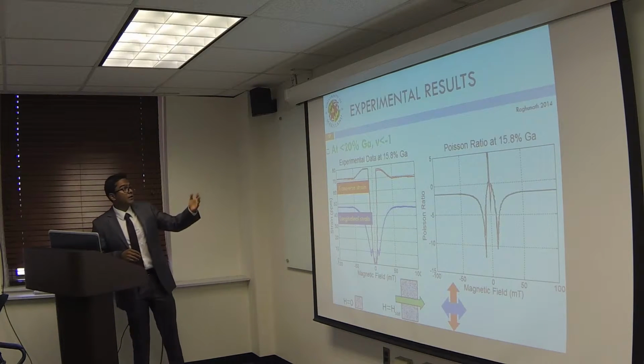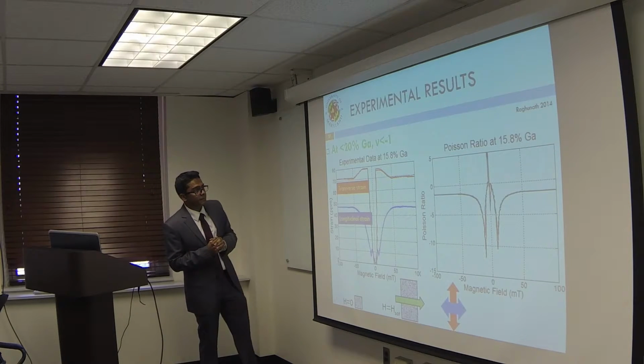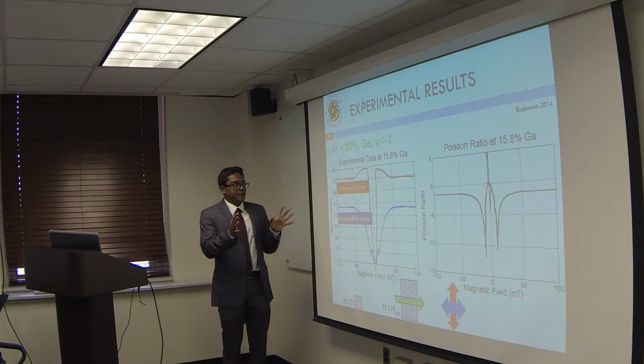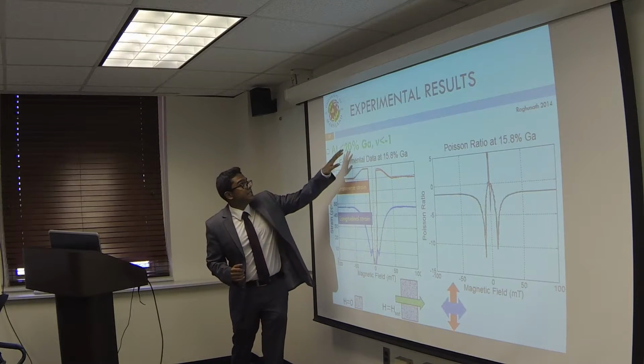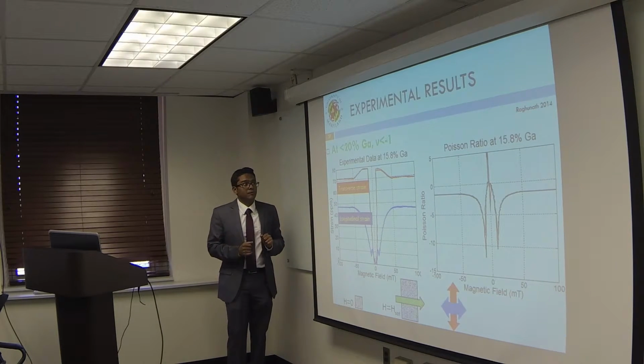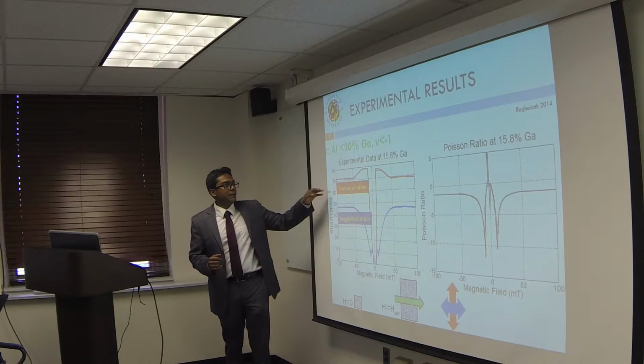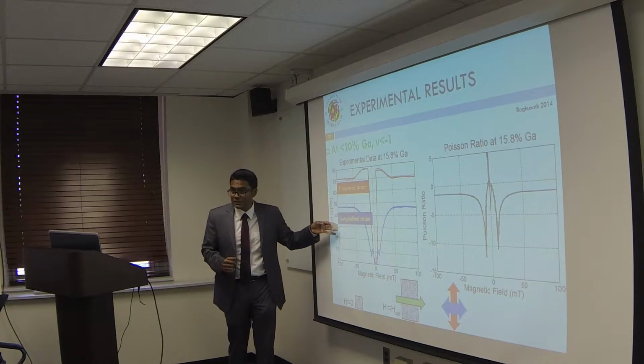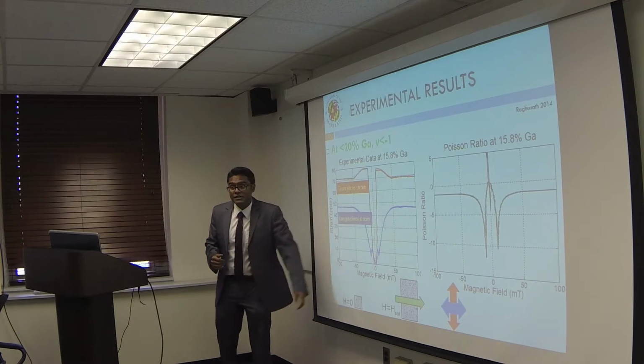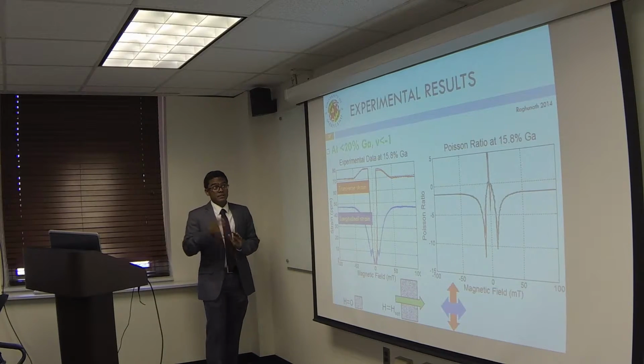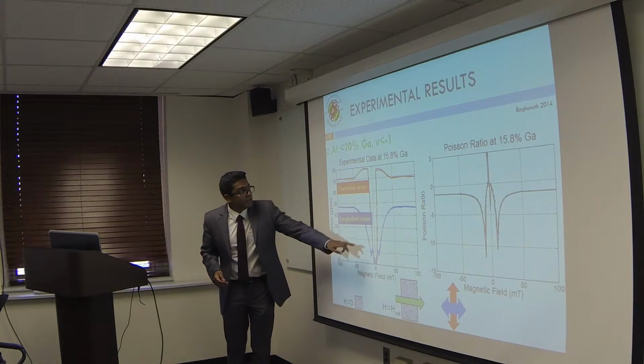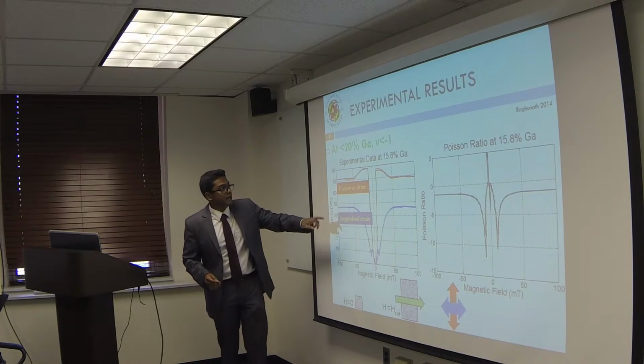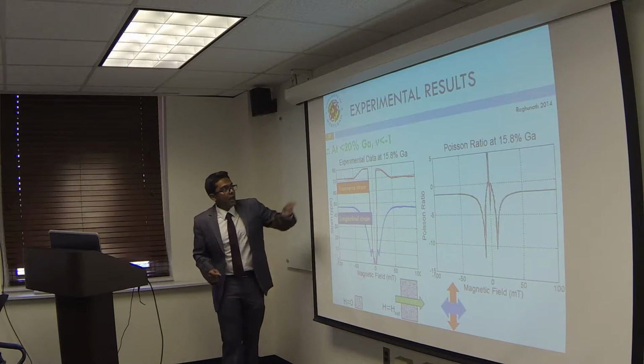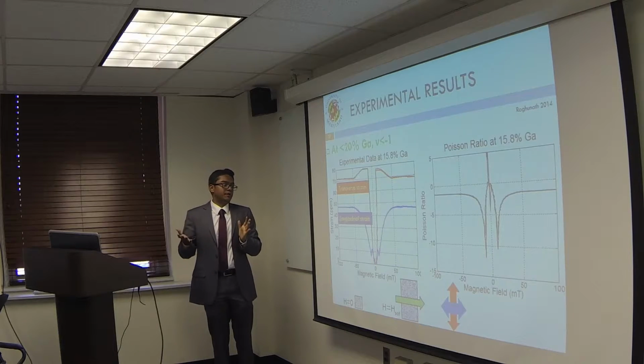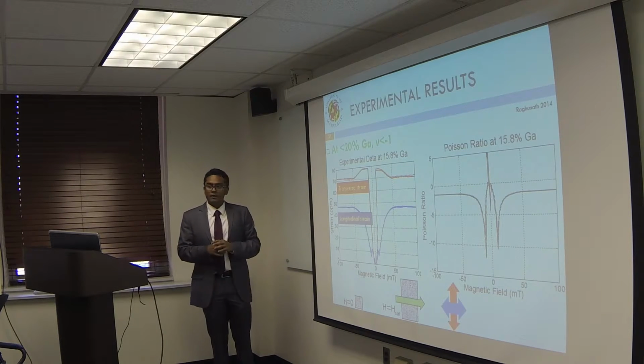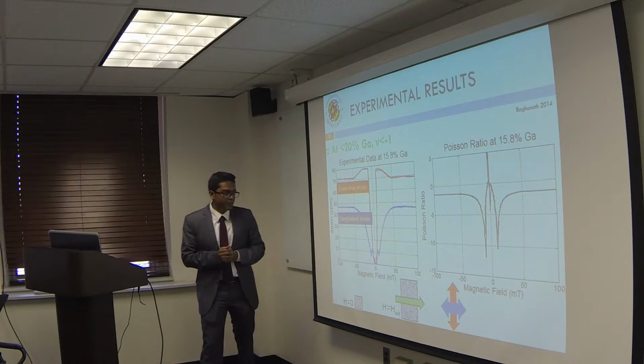And finally, here are the results from my experimental data. So this was very interesting. In samples with less than 20% gallium content, the value of transverse strain was much larger than the value of longitudinal strain, which made the Poisson's ratio value less than -1. So this is very interesting. And you can tell that there is a non-monotonic increase in the longitudinal strain and the transverse strain, and the values of strain at magnetic saturation were of the order of tens of parts per million.